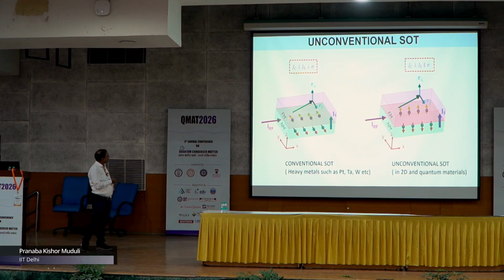The problem with this conventional spin orbit torque is that if you have a perpendicularly magnetized ferromagnetic layer, then in order to break the symmetry, you need to apply an in-plane field to switch. So this is a requirement because of the spin-orbit symmetry of the system.